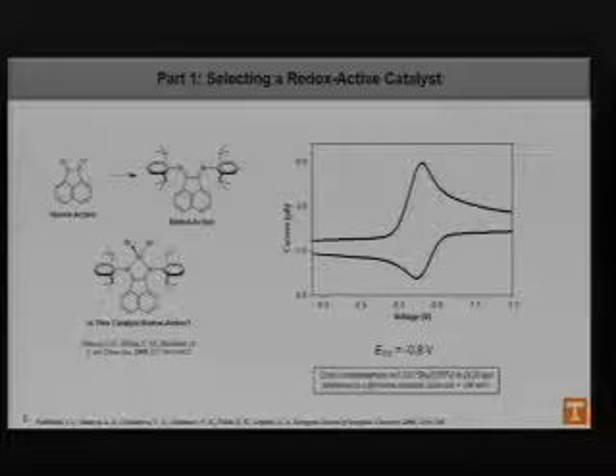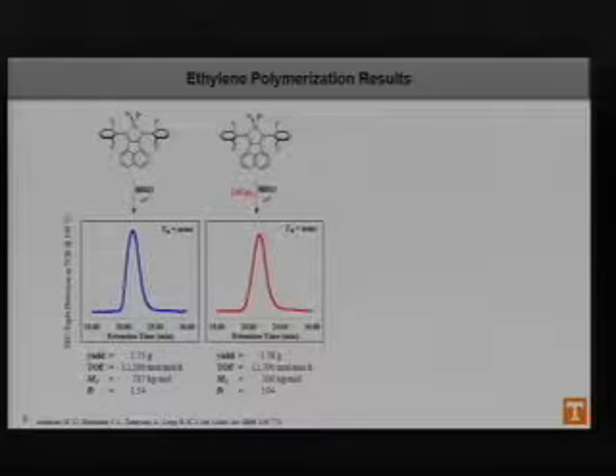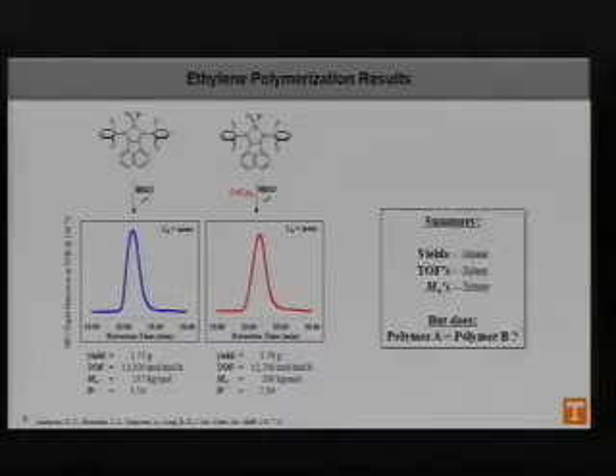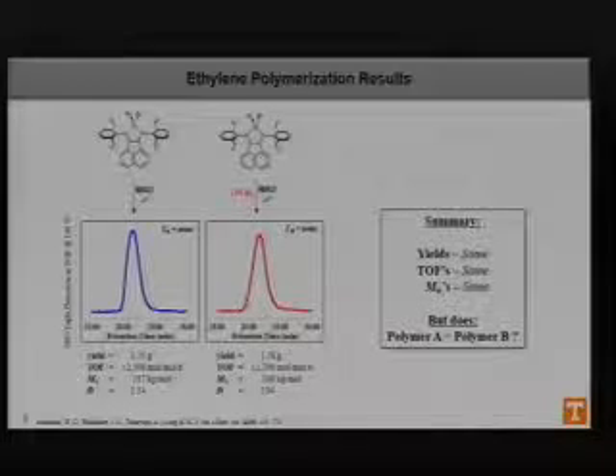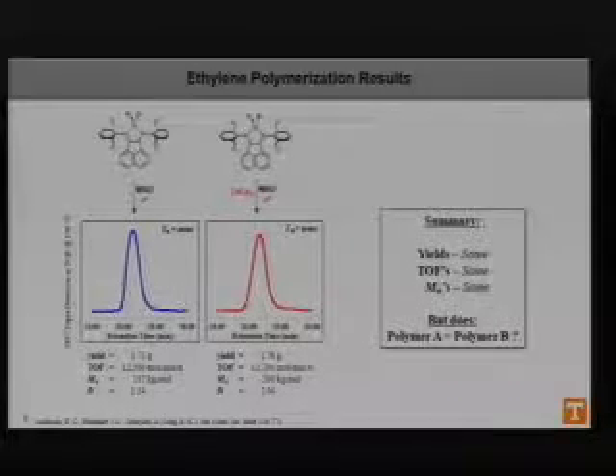So following that, we then began polymerization trials. We polymerized ethylene using this catalyst and MAO, and we obtained this GPC trace for that polymer. And then we repeated the same trial using the catalyst again, but this time we used cobaltocene, which is our reductant. This is what adds our electron to the system. And we essentially got the same GPC trace. And when you analyze the other results from it, the yield was about the same, the turnover frequencies were about the same, as was the molecular weights.